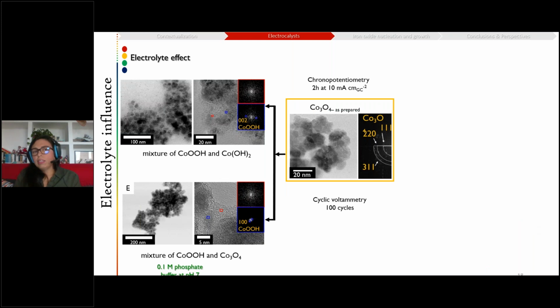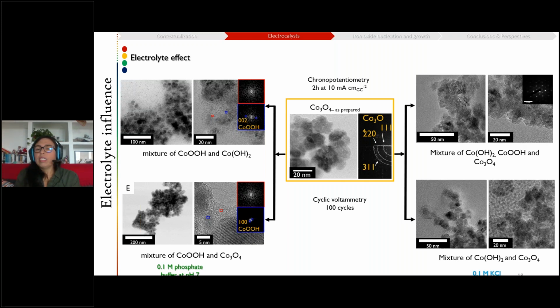So we were wondering if this is only a pH effect. So we decided to test a different neutral pH electrolyte, like KCl. And what we observe is that in the case of KCl, we don't see amorphization. We rather see an extended crystallization of the surface, leaning more towards the formation of monocrystalline surfaces, different from what we would see in the previous case. And we have different phases mixing within the same material, but no amorphous layer was found. So there is definitely an effect of the electrolyte on the amorphization process.